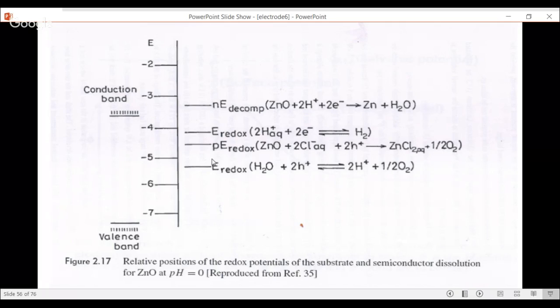Now, if the electrode itself is capable of undergoing some oxidation reaction, for example zinc oxide: zinc oxide plus 2 H plus and 2 electrons gives rise to zinc. So zinc 2 plus gets reduced to zinc. Zinc oxide is getting reduced, getting dissolved to give rise to the zinc ions. So if the potential of this redox reaction is less positive with respect to the oxygen evolution potential, that will be the preferable reaction, because the free energy change of this will be more negative compared to the oxygen evolution reaction.